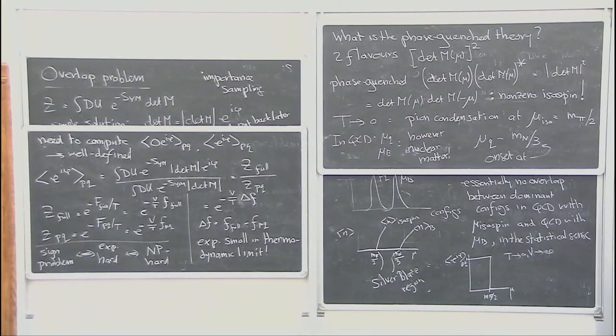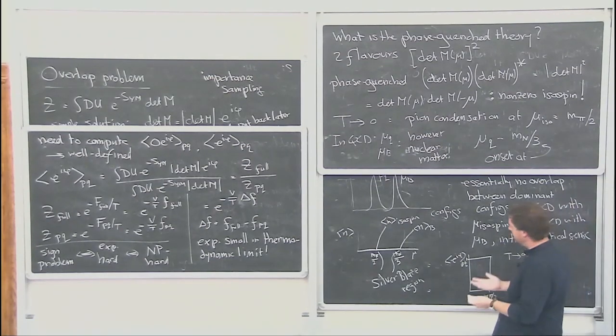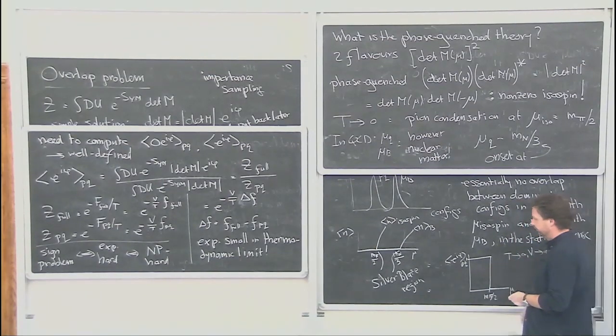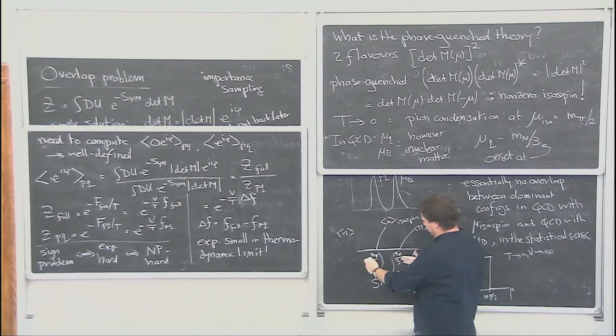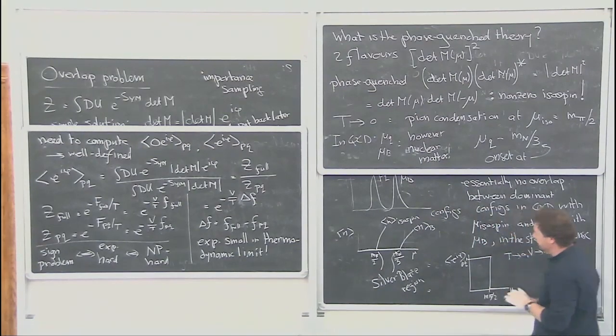So there are approaches where you approximate the fermion determinant by treating the quarks as being heavy. So you do, for those who know, a hopping expansion, which you can do for heavy quarks. And then you can actually do simulations. The sign problem is mild, which means this is close to 1. But essentially what you're doing is that these regions are almost overlapping here. So that's not a real interesting range to study. Yeah, but that's true.